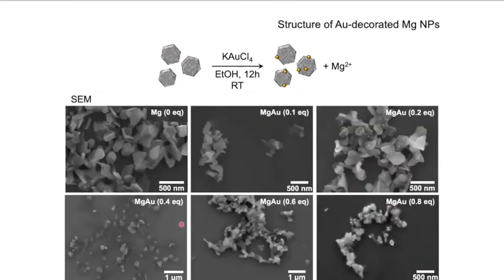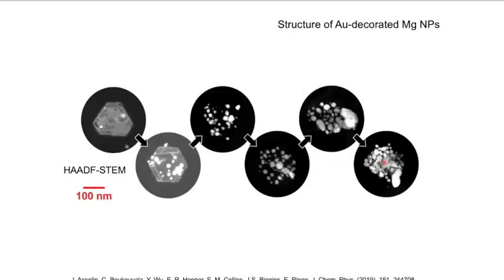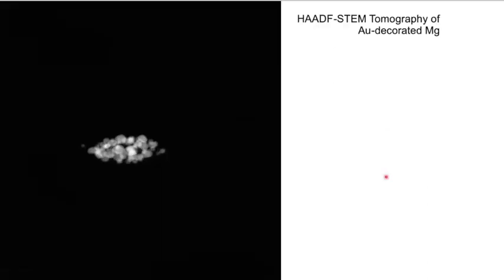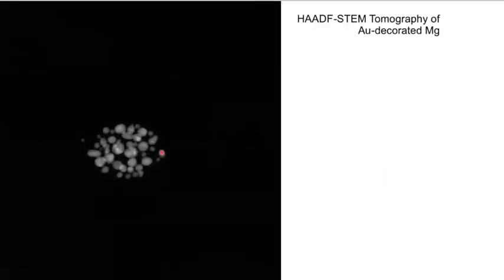So this works. The more gold we put, the more gold particles we get, and these are decorated on the structures. We don't find gold floating around alone. There's nothing to reduce it in the flask. There's only the magnesium as the source of electrons. So again, the more gold, the more stoichiometry of gold, the more gold on the structures. And here's a tilt series, for instance.